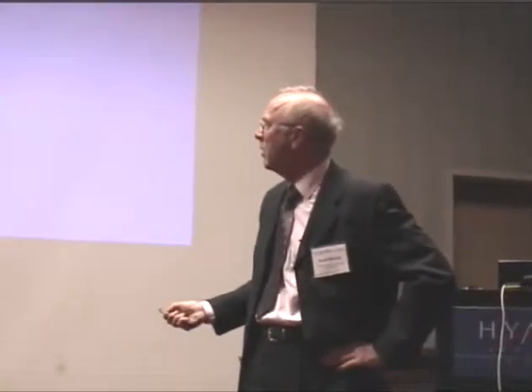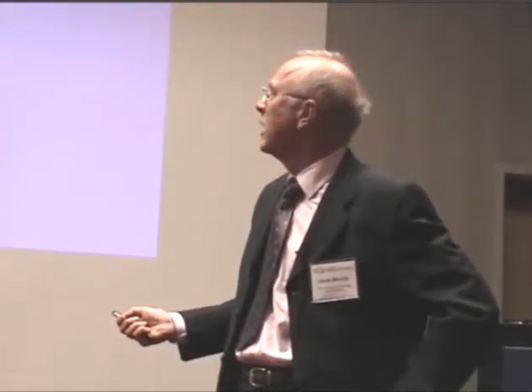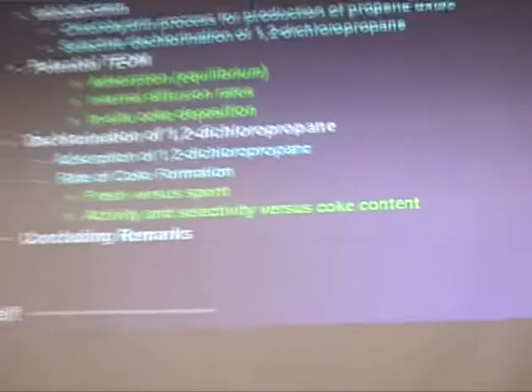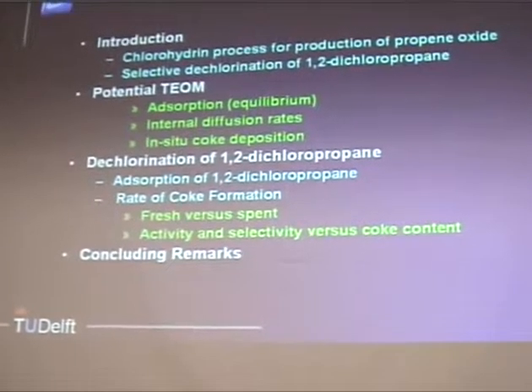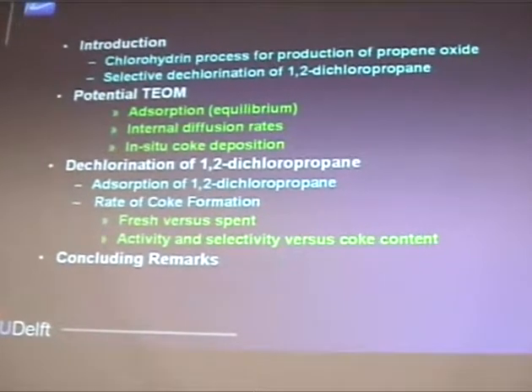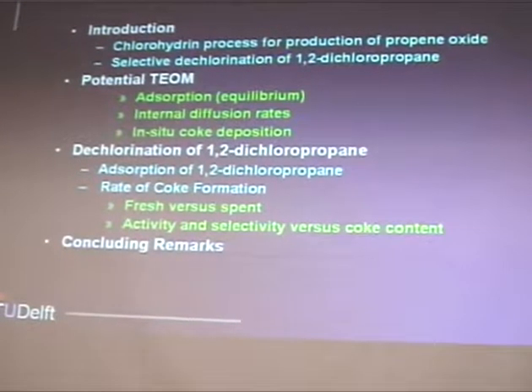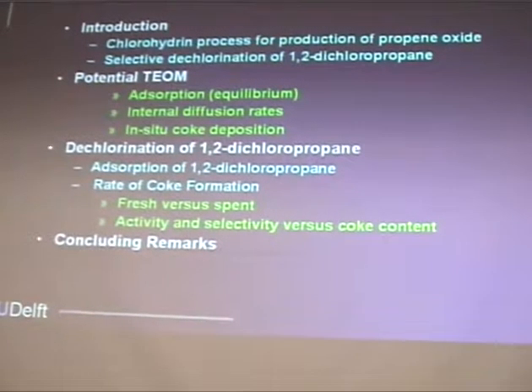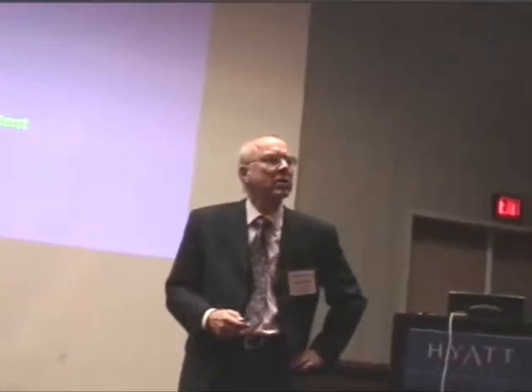We used it a lot. And of course, we go to in-situ coke deposition. And that's then the example I treat short. That will be the hydrodechlorination of 1,2-dichloropropane. I show you adsorption, rates of coke formation, and we have a certain objective. I'll explain that. So it's the fresh and the spent catalyst, and also it has a rather dramatic response to coke deposition. Everything changed, not only the activity. That's interesting, and I come to the concluding remarks.